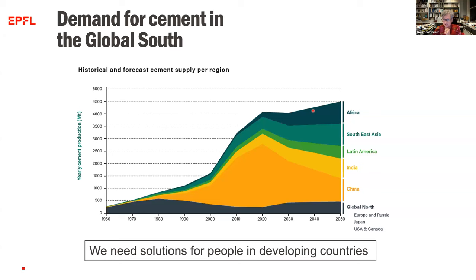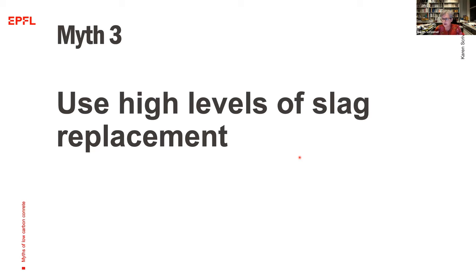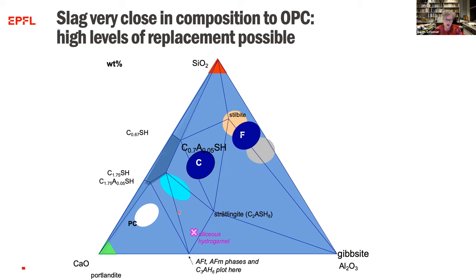So the next myth I'm going to look at is quite a simple one to deal with. Should we use very high levels of slag replacement? Well, we can use high levels of slag replacement because the composition of slag here is very close to that of Portland cement. It's in the area of calcium silicate hydrate. And this means that substitution levels up to even 80 or 90% can be used and are allowed in many norms. However, the problem is that we have a limited availability of slag.